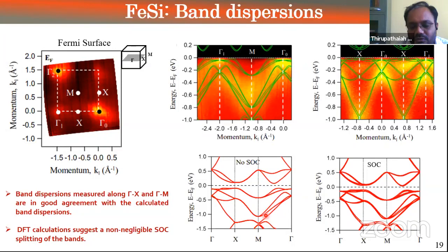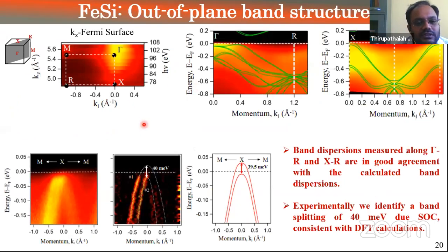And here we are also showing the band structure without SOC and with SOC. Although there are no quite drastic changes, there is a little bit of splitting in the bands with the inclusion of SOC, which I will come back to later. And then in ARPES measurements, we can also measure along the Kz direction just by changing the photon energy in the normal emission position. So this is such a Kz map measured in the gamma X R M direction.